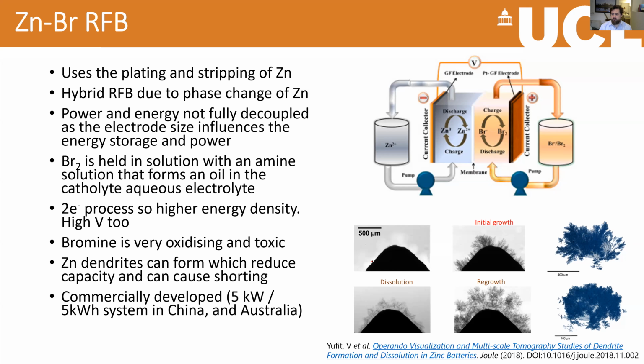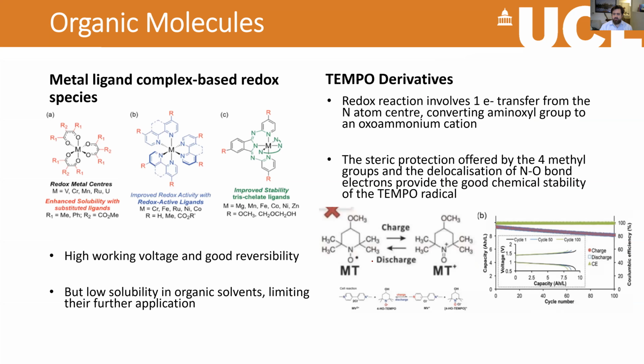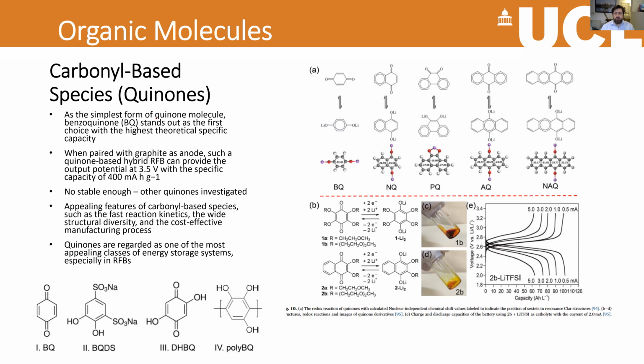Okay. So I'll just quickly go on to some of the other types of chemistries, but as I say, there's a huge variety of different things. One of the key interests recently is organic molecules, and this is for a number of different reasons. They're very tunable. You can synthesize lots of different types of organic molecules that might have different cell voltages, and also crucially, they might be a bit more bulky. So you can look at some of these metal ligand complexes here, kind of larger molecules. And so this crossover effect through these permeable membranes can actually be reduced with good engineering of these molecules. And there's lots of different types of organic molecules that you can use, and actually quinones are some of the most promising. And there's been some really key research done on this very recently in the last 5 years or so, looking at quinones.